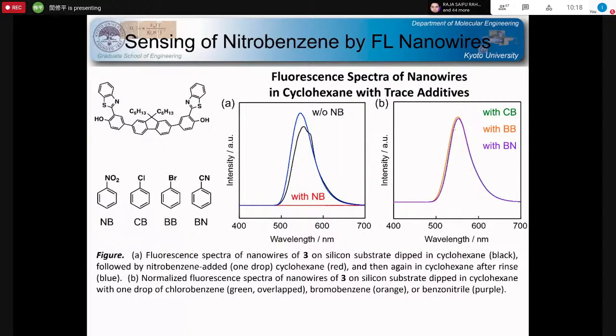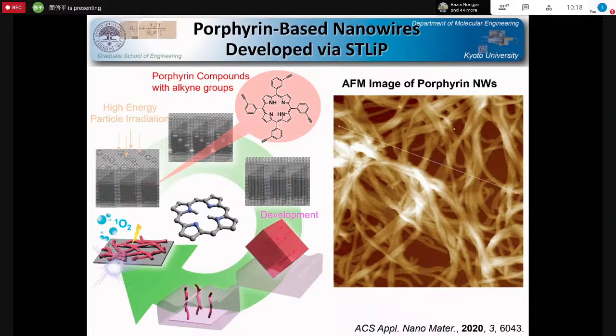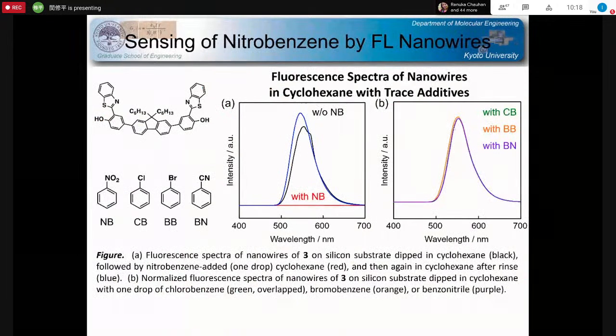So the question is whether our nanowires can be applicable for the sensing of explosives or not. And we have tried to check the emissivity of the nanowire. And after the exposure to nitrobenzenes, as seen in the red lines, the emission from the nanowires was completely quenched. So reflecting the extremely wide surface area of the nanowires, this kind of nanowire system should be expected to act as a highly sensitive sensing platform in the future.